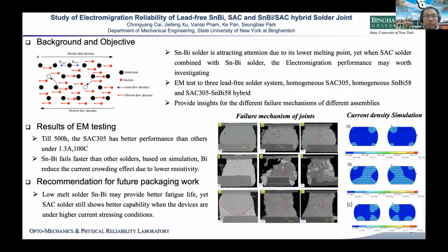After performing finite element analysis, we can see that the tin bismuth solder has a reduced current crowding effect, because the bismuth provides smaller resistance. Yet the tin bismuth still fails earlier than the homogeneous SAC305, which suggests that the intrinsic properties of tin bismuth and SAC305, like activation energy, differ during the electromigration test. So for packaging recommendations, although tin bismuth solder might provide better fatigue life and a lower melting point, when it comes to high power electronics, where devices are under higher current stressing, we still need to pay attention as tin bismuth may fail earlier. From one perspective, it is because of its faster diffusion process and activation energy.